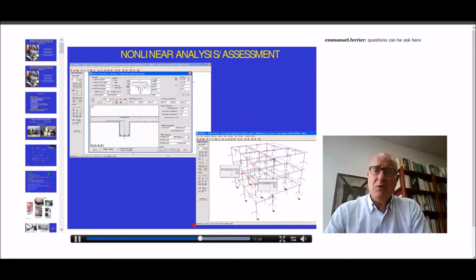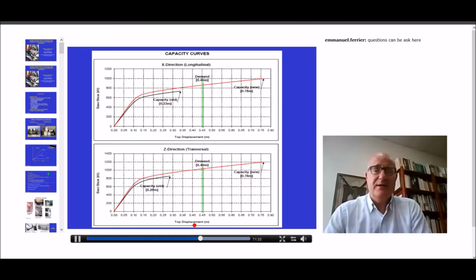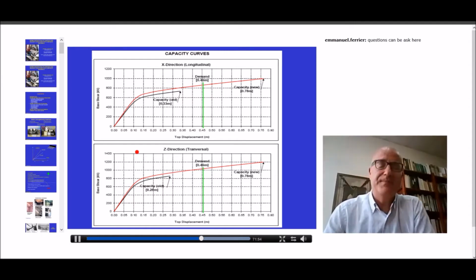The objective of the retrofitting was to increase the shear resistance in many structural elements, as well as the ductility. What you see here is the base shear in the two principal directions of the building as a function of the top displacement. In black, you see the capacity curve of the building before retrofitting in two directions, and in red, the capacity of the same structure after retrofitting, which shall be described in a second, the way it was done. Again, take a look that there is only an increase in the deformation capacity. There is practically no modification of the stiffness.